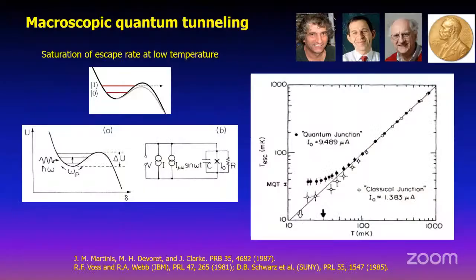Okay. So in the 80s they succeeded to see macroscopic quantum tunneling. That means when they tilt this double well potential by applying, in this case, a current bias to the Josephson junction and tilt the cosine potential, in each well of the cosine potential, basically the state of the whole circuit is quantized. And then they succeeded to see the effect of the quantum tunneling across this potential barrier, and a saturating tunneling rate at low temperature.